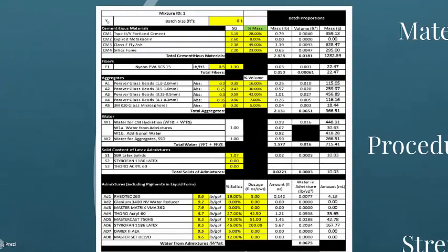Cementitious materials used were Type 2/5 Portland cement, Class F fly ash, and silica fume. We chose to add more Class F fly ash than cement in order to increase compression strength and decrease permeability. Fibers used were PVA fibers, intended to increase tensile strength and reduce cracking. Aggregates used were expanded glass beads ranging from 0.03 millimeters to 2 millimeters, and K20 glass microspheres used as a fine aggregate.